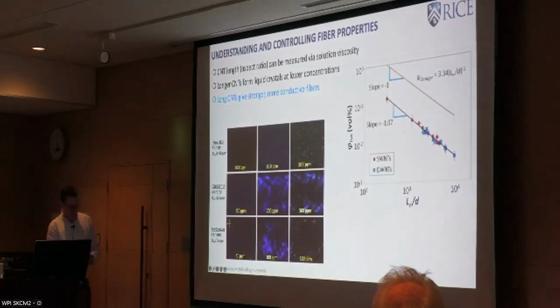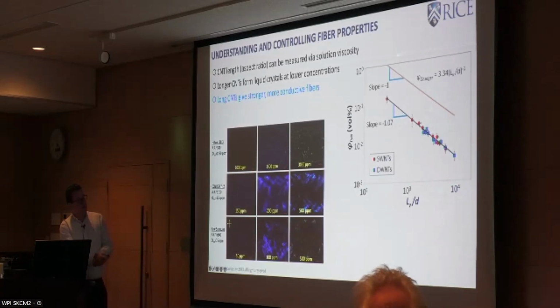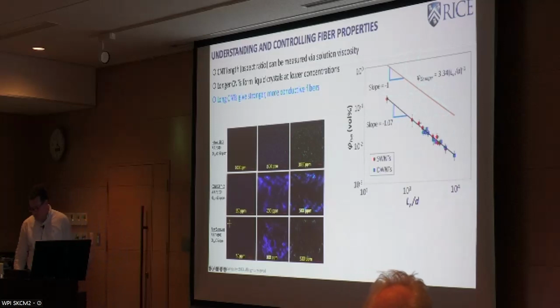Lots of things happen that are not surprising. The transition from isotropic to liquid crystal goes with the aspect ratio, although it follows a parallel to the Onsager theory by about an order of magnitude lower because of the polydispersity of the nanotubes, which is again something that is consistent with the theories for polydisperse rods.